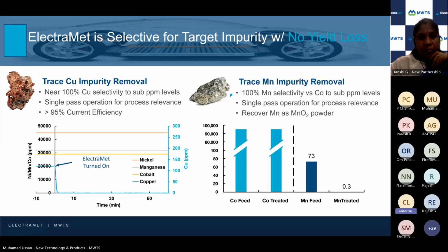So here's giving some real world examples of this black mass leachate for these two different streams. The one on the left is a client that wants to make the cathode active material directly. So they have the mixture of their nickel, manganese, and cobalt. They don't want to lose any of that. They just want the copper out. So we're flowing this black mass leachate through our system, and as soon as we turn it on, you can see the copper comes down, and we're hitting the specifications of less than 2 parts per million. And we don't touch the cobalt, the nickel, or the manganese, so that their product is in the right ratio. They're good to go. All right, using a single pass operation, very high efficiencies.